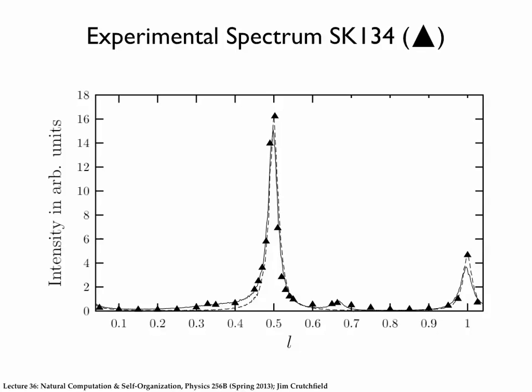And if we didn't have any of this other stuff here, and these were just strictly very sharp Bragg peaks, you would say, oh, I've seen that before. That is 2H, the period 2 hexagonal. So this naively looks like what you would think. Back in the day, this looks like a 2H crystal that has some kind of stacking, where there are regions of the crystal that break the regular stacking sequence of 2H, that are somehow disordered, that are somehow broadening these diffraction peaks. And when we do epsilon machine reconstruction, this is what we get.